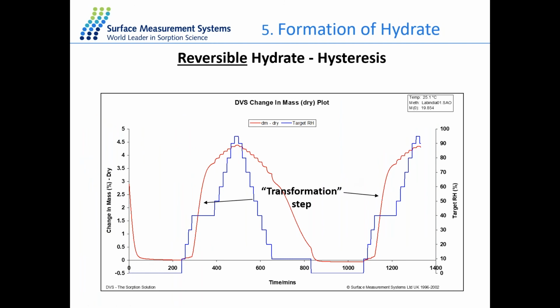And the next application I would like to introduce is about the formation of hydrate. Basically, it's an uptake at a certain step that is due to the formation of hydrate for pharmaceutical material. So here we have the sample. We perform the sorption experiment with the step method we introduced previously. This sample is pretty much stable below 40% RH, at almost around 0.3 uptake. And then at this single step, it can pick up lots of water. This is because of the formation of the hydrate.